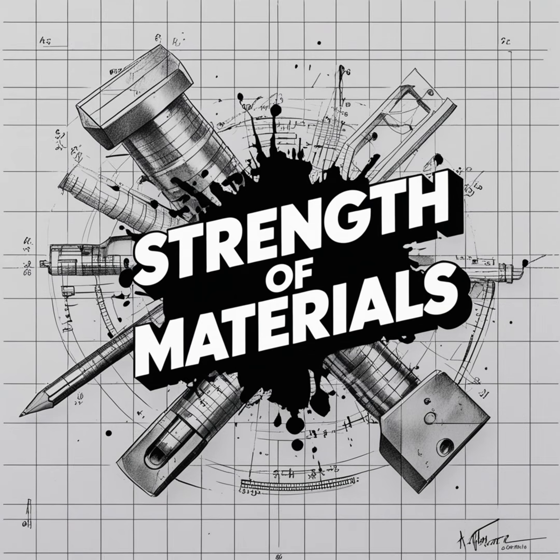But sometimes a component is subjected to absolute hell. I'm thinking of the turbine blades inside a jet engine experiencing massive thermal expansion, or the metal around a sharp bolt hole in an excavator bucket. In those extreme situations, significant plasticity is involved. The material isn't just springing back, it is physically yielding. It is stretching and compressing permanently, back and forth, on every cycle. That sounds rough on the metal. It is. And when this happens, the component's lifetime is going to be incredibly short, maybe just a few hundred or a few thousand cycles. This is low cycle fatigue, or LCF.